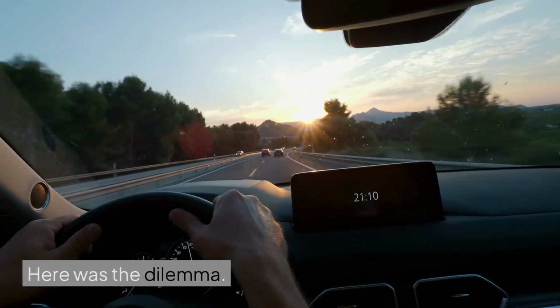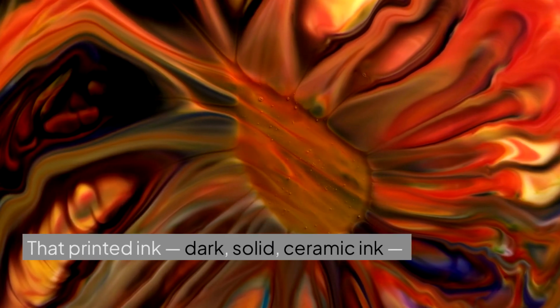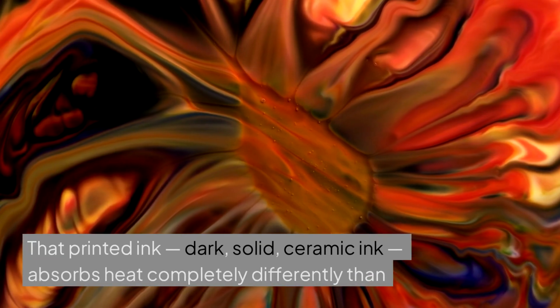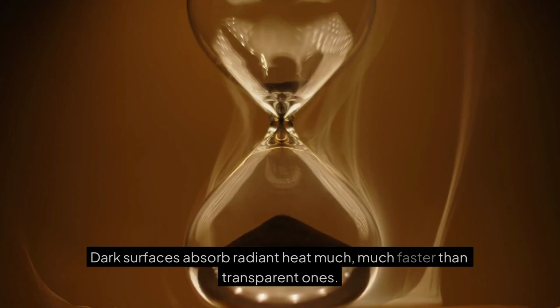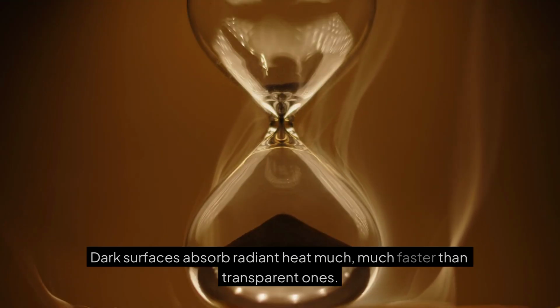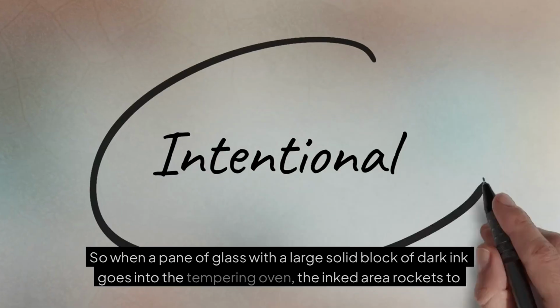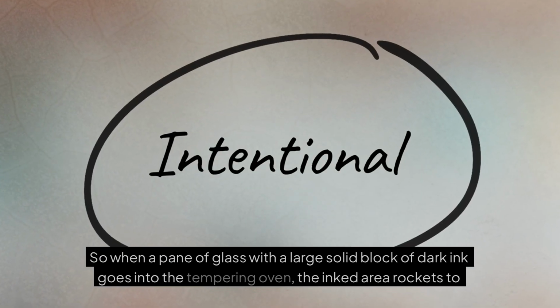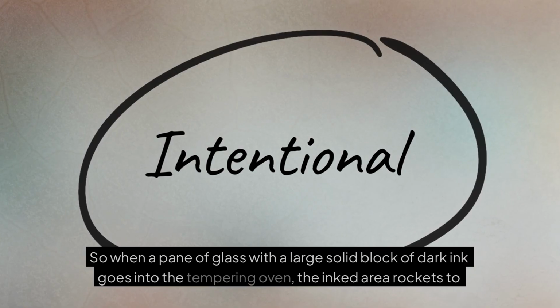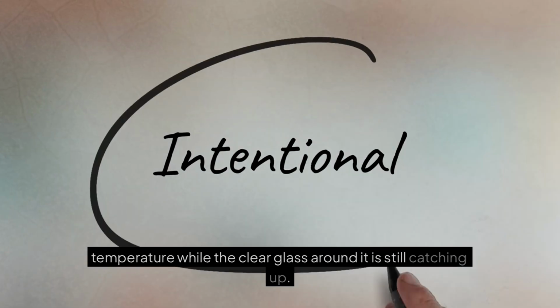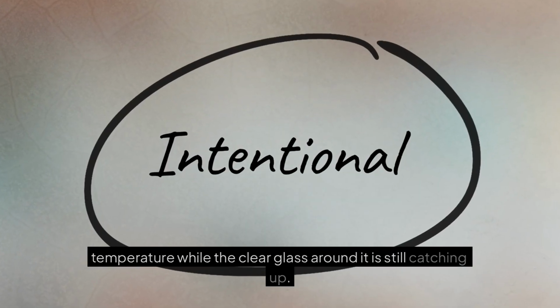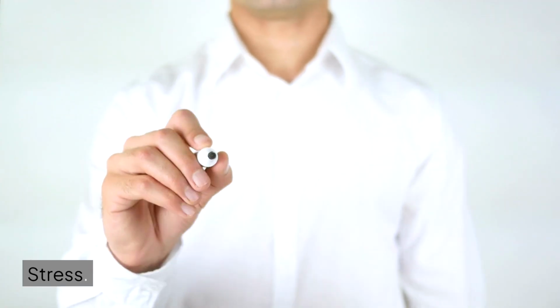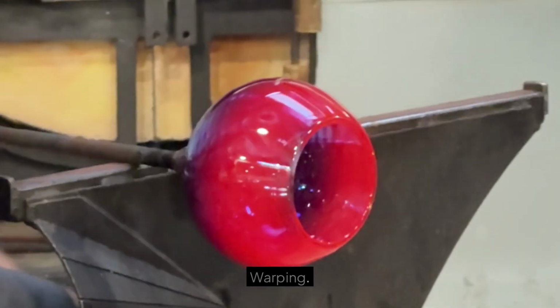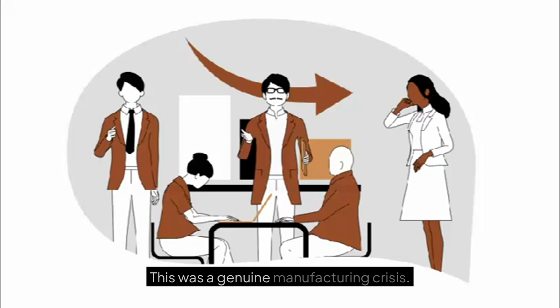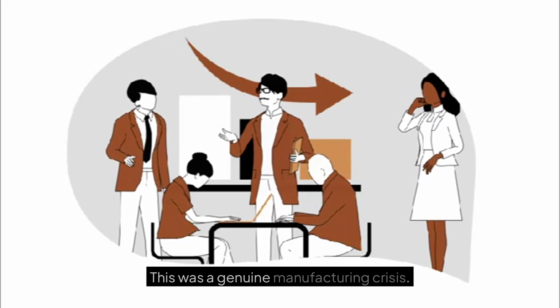Here was the dilemma. That printed ink, dark, solid ceramic ink, absorbs heat completely differently than the clear glass surrounding it. Dark surfaces absorb radiant heat much, much faster than transparent ones. So when a pane of glass with a large solid block of dark ink goes into the tempering oven, the inked area rockets to temperature, while the clear glass around it is still catching up. The result? Stress, cracking, warping, ruined glass. This was a genuine manufacturing crisis.